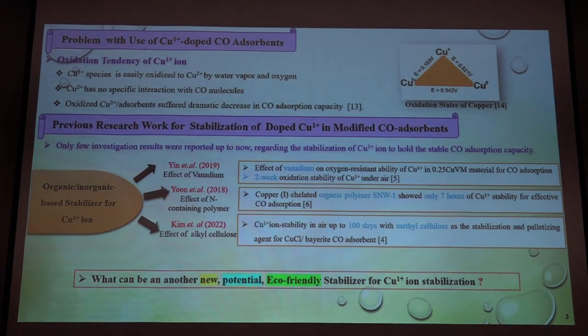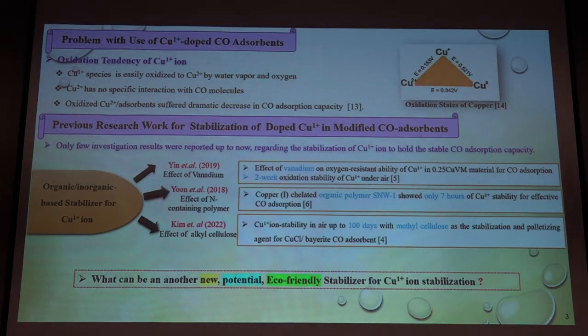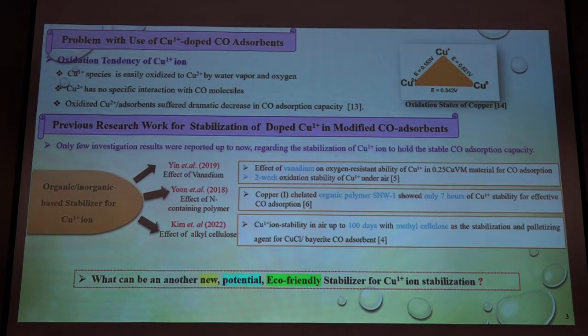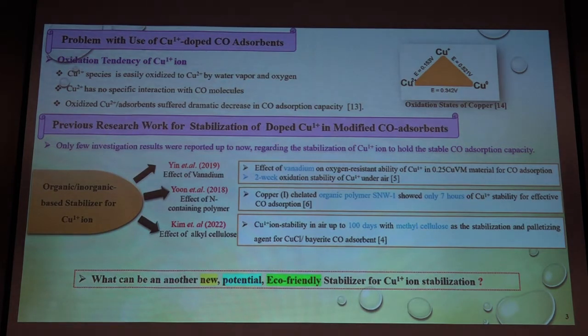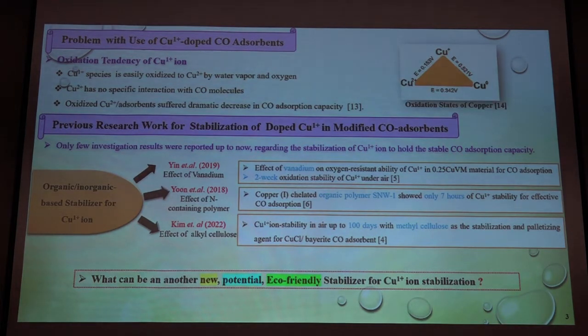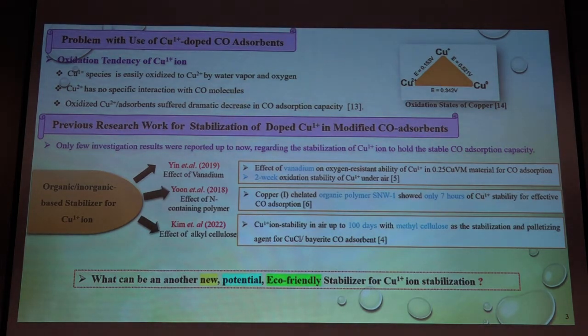However, the use of copper-1 chloride can be problematic when it is exposed to the air, because copper-1 chloride is readily oxidized to the copper 2 plus ion, which cannot react with CO anymore. That's why the CO adsorption capacity can decrease. So, in order to solve these problems, only a few research works have been reported till now, and they usually use an inorganic stabilizer for copper-1 chloride stabilization to get a stable CO adsorption capacity even under moist conditions.